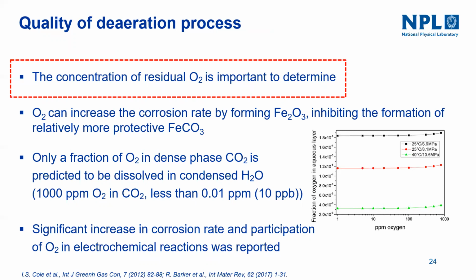So oxygen should not really play a key role, but several studies have indicated that oxygen takes part in electrochemical reactions and also significantly increases the corrosion rate. So one thing is we need to check on the quality of the deaeration process, or understand more whether there is any real effect at this concentration limit.